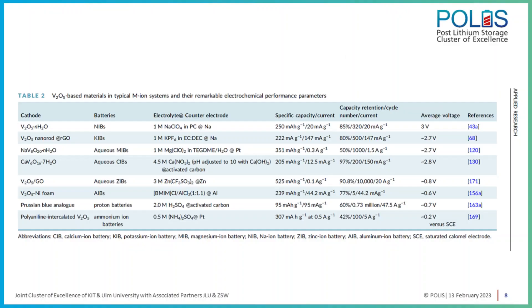There are still some challenges, of course, because when moving from lithium to post-lithium, everything is different. For instance, the size of the ions is bigger — we need to intercalate larger ions like sodium, or potassium which is even bigger, into the interlayer space of vanadium pentoxide. There are also progresses for zinc batteries, but here we are speaking about aqueous batteries. The capacity in zinc-ion batteries can reach about 500 mAh/g, but the cell voltage is limited by the stability of water.